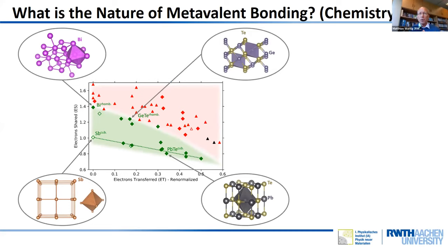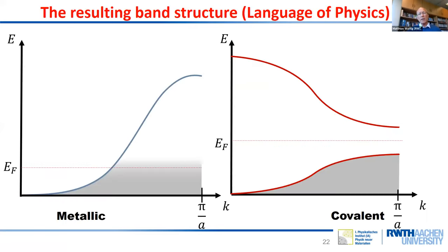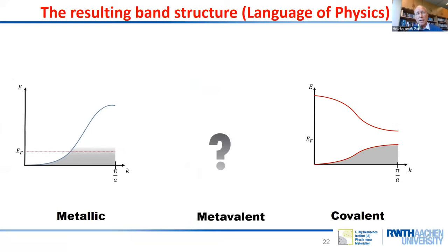So what is striking from the point of view of the chemist is the fact that all of these materials in this green region here have something in common in their atomic arrangement. They are all octahedral-like. So they have, on average, six nearest neighbors, sometimes with some distortions, but this is what they all have in common. And now we can look at what this will lead to regarding the band structure. And everybody in this audience can easily draw a band structure for a typical metal. This is a typical band structure for a metal. On the right-hand side, we have the band structure for a covalent material where there's a well-defined band gap. Now the question would be, hey, what is the band structure of a metavalent material? So let's talk about these materials from the point of view of physics.